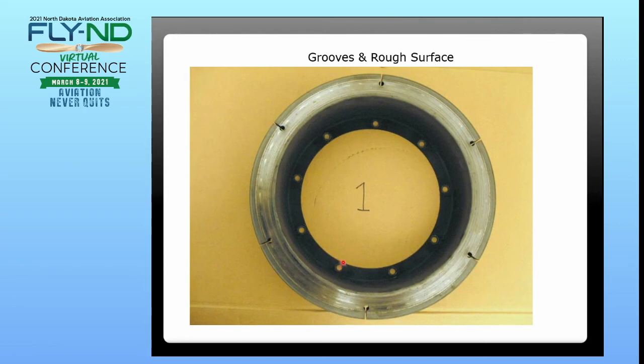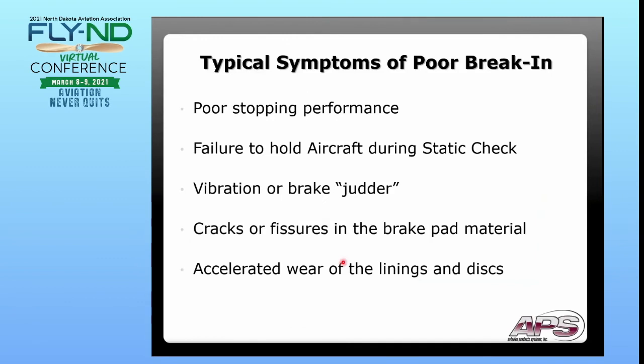So from there, the symptoms of the poor break-in. Okay, you're going to have poor stopping performance, failure to hold during the static check, the static run up, and vibration or judder within the pedal. That's going to be from the glazed part rubbing up against the part of the brake disc that does not have the material transferred. On the semi-metallic side, you're going to have cracks or fissures in the brake pad material, which is all going to cause an accelerated wear of the linings and the disc.